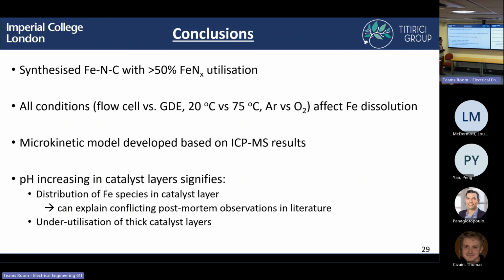And also, importantly, it's quite clear that we must be underutilizing thick catalyst layers. These iron nitrogen carbon catalysts are typically around 60 to 150 microns, so we use 60 here. If people are using a 100 micron thick catalyst layer, most of that isn't being used because the pH is increasing significantly, and so this is really limiting the performance of the fuel cell.